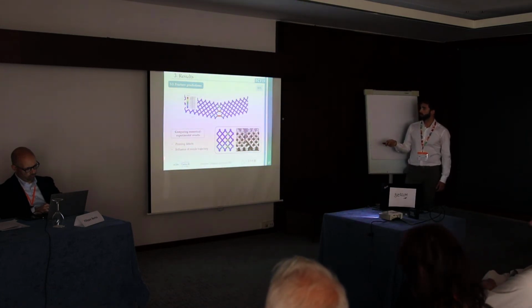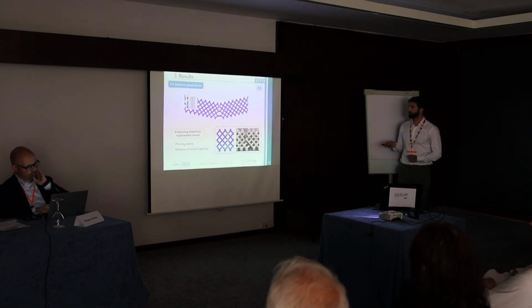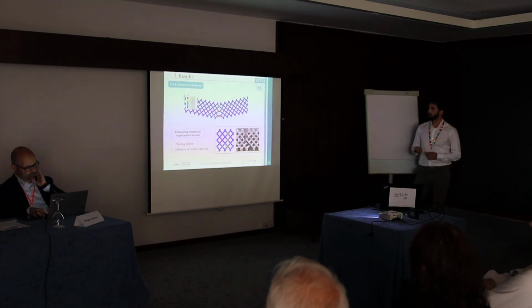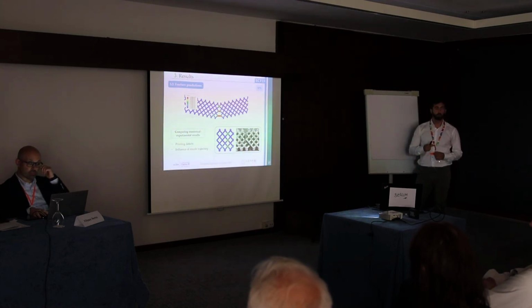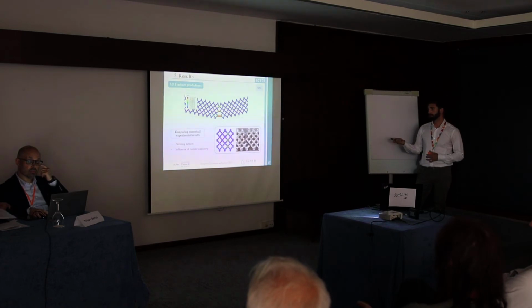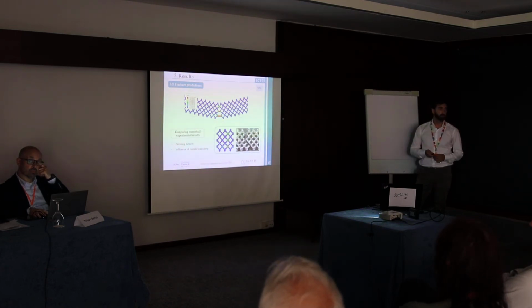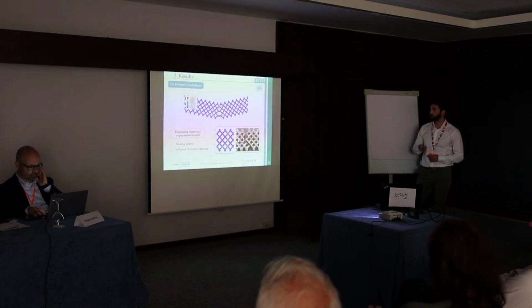Okay, if we compare the numerical and experimental results, we can see that the result is not the same. What does that mean? Well, it could be explained by the fact that the numerical model has no printing defects. It's a perfect, repetitive geometry for the grid pattern, and the opposite happened with the 3D printed specimens, with some critical imperfection that could change the crack path.